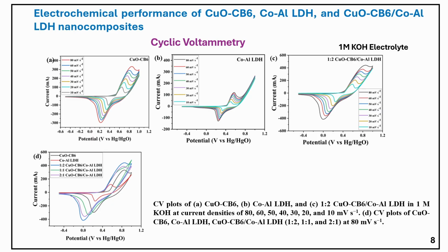The CV plot of bare cobalt aluminum LDH reveals an anodic peak at approximately 0.57 volt, signifying the formation of cobalt 3 oxyhydroxide, that is CoOOH. Besides, a cathodic peak during the reverse scan at 0.24 volt, which is attributed to the reduction of cobalt 3 to cobalt 2. The CV plot of bare CuO-CB6 reveals a pair of redox peaks at approximately 0.85 and 0.218 volt, confirming the formation of copper 3 oxide and the reduction of copper 3 to copper 2. The clearly defined peaks confirm the remarkable electrochemical reversibility of the active materials.